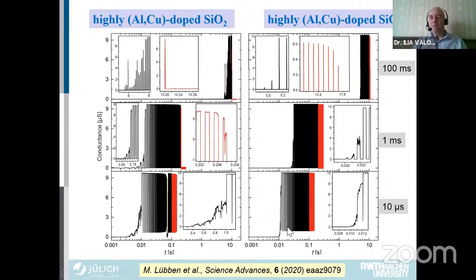So you see the very short pulses, none of it forgets, but one is switching faster than the other. But then where the bond is a bit weaker, then you have already forgetting. Here you forget, and here you still don't forget. And when you go to very long pulses, then you see that the forgetting is very fast, and here it's still not very fast.